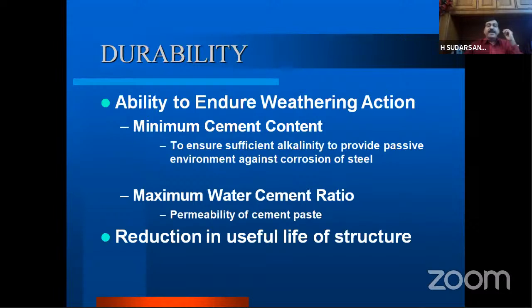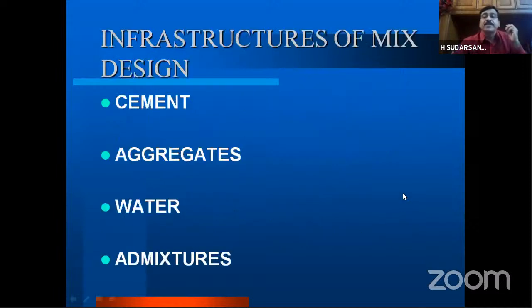So you have to place a limit on the maximum water cement ratio, because if you go on increasing the water cement ratio, the permeability of the cement paste increases. If the permeability increases, there is more likelihood for the environmental things to penetrate into the concrete easily and attack the concrete and the reinforcement steel. So we have to have a limit on the maximum water cement ratio. How the reduction in useful life of the structure can be controlled, and how to achieve that the structure performs for its design life period. These are all the durability aspects which you need to consider.